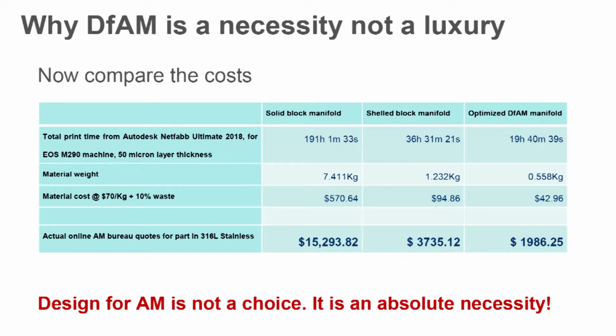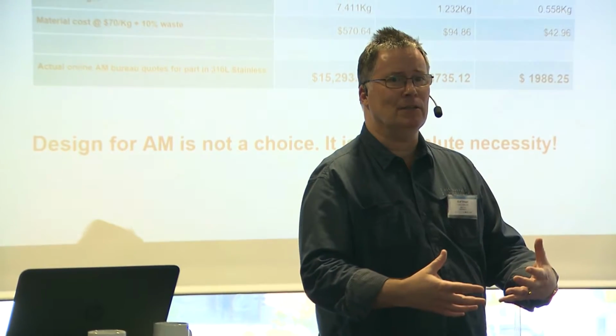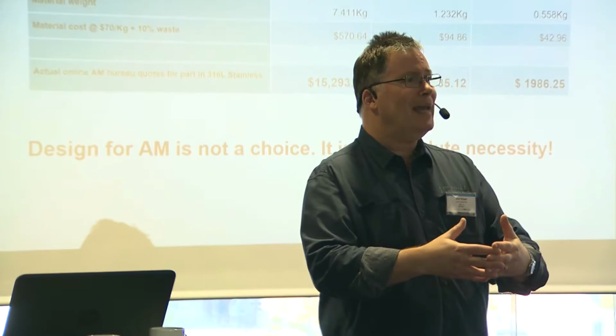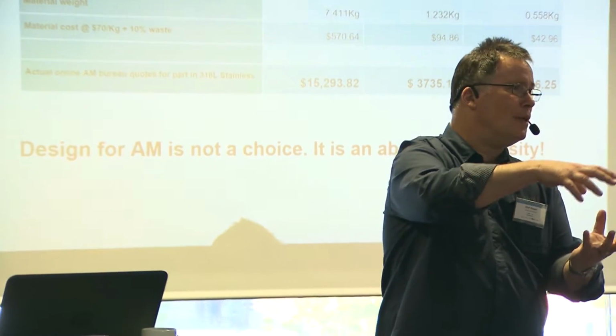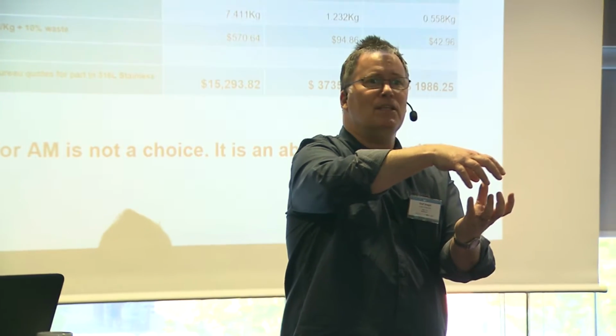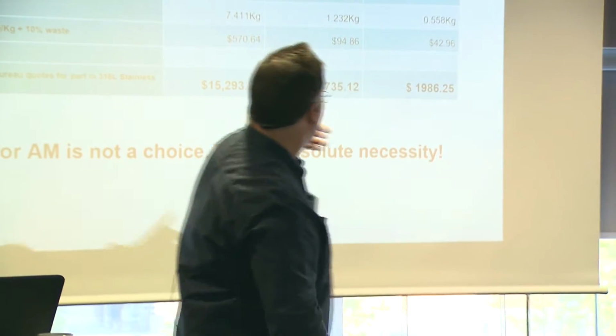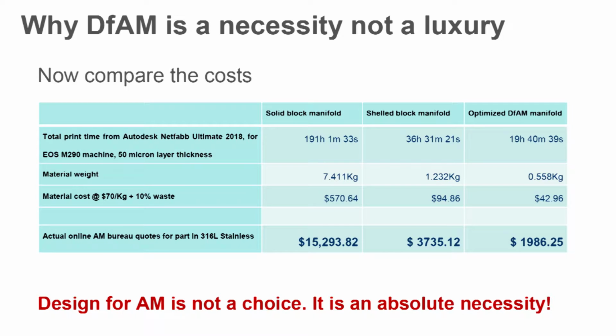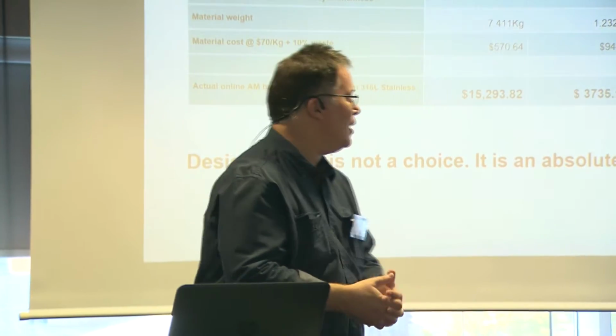So where it gets interesting, which is the point of the whole argument, is you start to look at the cost. Now, these costs down the bottom, these are actual quotes I got about 2 weeks ago from Sculpteo, one of the online services that offers selective laser melting as a service. The standard block manifold, $15,000 to print a block of steel 100 by 100 by 100. That's heart attack material. And these are real prices. Now, I cannot think of any argument, no matter how complex it is, where a 100 by 100 block of steel is worth 15 grand. It just isn't. Contrast the shelled one, 3,700, and the designed one, just under 2,000. I still think way too expensive, but that's because material prices are still pretty high.